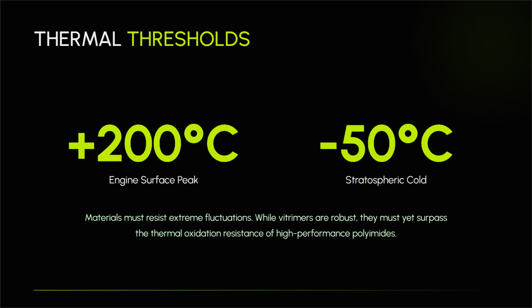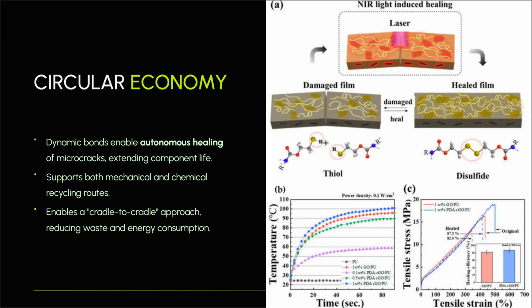Furthermore, exposure to moisture, ultraviolet radiation, and corrosive aviation fluids can accelerate matrix degradation. Therefore, developing molecular architectures with higher glass transition temperatures, while integrating robust protection strategies like UV stabilizers and antioxidant additives, is essential to guarantee long-term survival in harsh operational environments. Despite these challenges, the true commercial appeal of Vitrimers lies in their capacity for self-healing and their contribution to a circular economy.